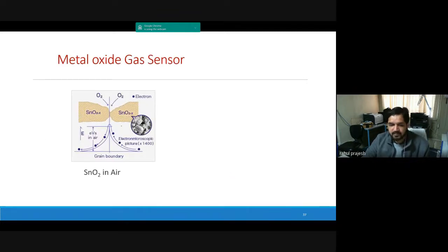If you go more deep into it, the resistance change is basically related to the grain boundaries of the material. These materials are most of the time polycrystalline in nature, and polycrystalline materials have grain boundaries. At these grain boundaries, you have a barrier created. The electron is trying to move from one side to another, but because of these boundaries, you will see some resistance, so there will be a barrier potential. Once you have oxidizing nature, what will happen? The oxygen will absorb at this particular point and electrons will be taken. So this barrier will increase, because you'll have fewer electrons over here, so that part has more resistance now.